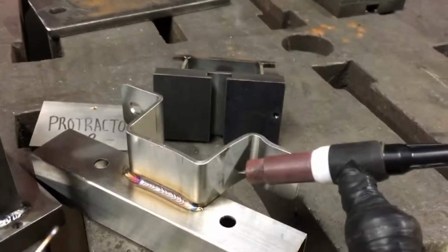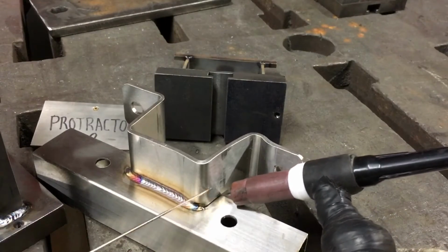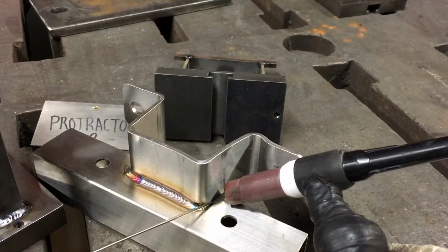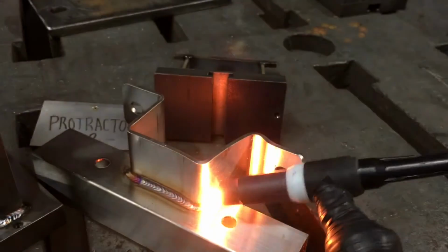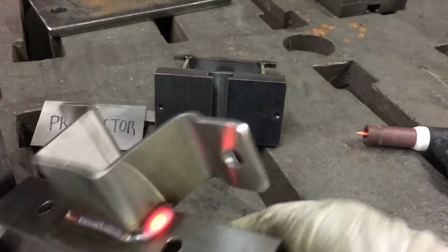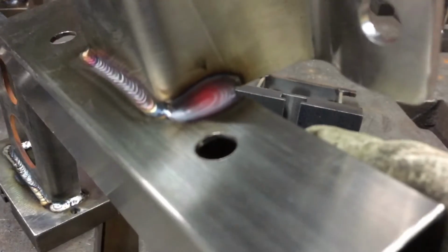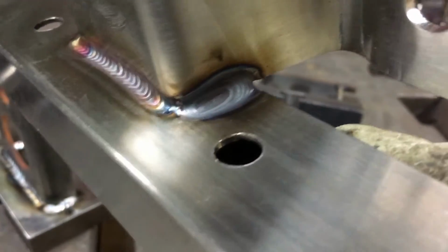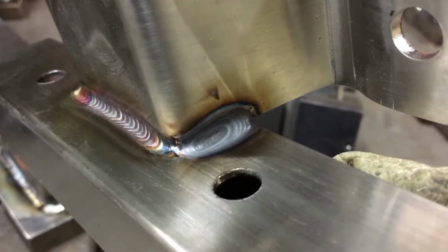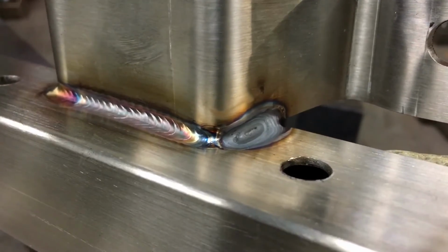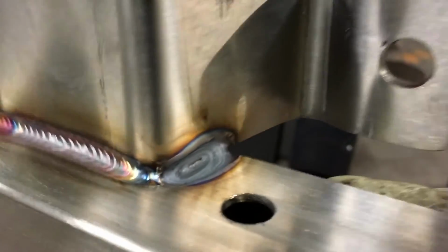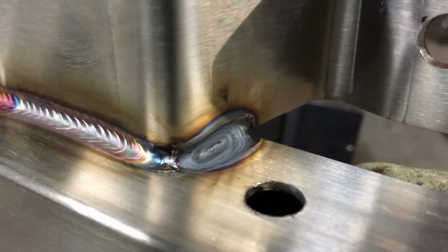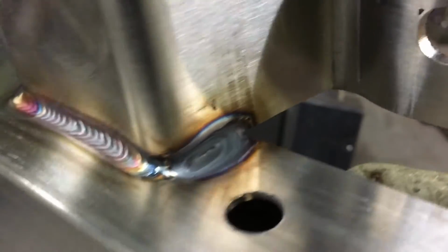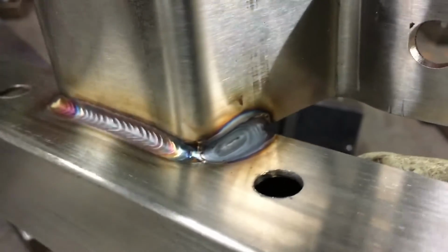I'm going to show you a portion of the weld that won't be able to get cleaned up when the chromium gets burnt. So if I pull away right away, I have it running pretty hot. If I pull away without the gas on there, you can see it goes gray, and that's not going to get cleaned up. So right off the bat, you're going to have to grind that and do an abrasion. That's where the chromium's all burnt.